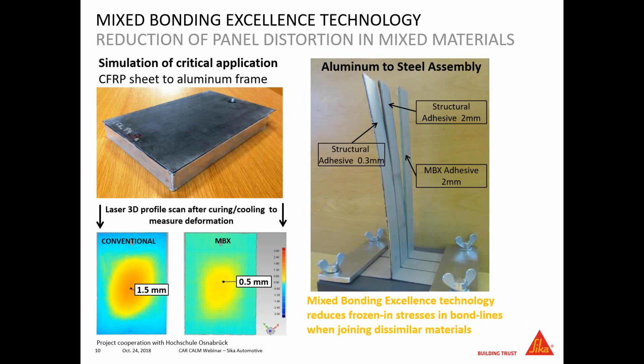On the left side, you can see an aluminum frame which is bonded to a CFRP sheet. And if you're using a conventional structural adhesive, the CFRP panel starts to deform. That can be observed with a 3D laser profile scan. And you can see that in this example here, we had a deformation of 1.5 millimeters at the center of the CFRP panel. If you're bonding this component with an MBX material, with a more flexibilized material, the adhesive can absorb way more of the strains, and only a deformation of 0.5 millimeters resulted after the cure.